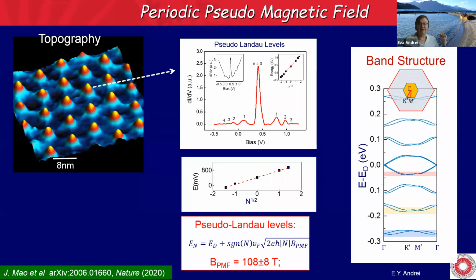Now, this is the band structure that we get. Of course, something like this will give you a flat band. This is a simulation of the band structure for this pseudomagnetic field, and you get a sequence of flat bands. In principle, if you can bring the Fermi energy into these flat bands, you should be able to open a pseudo gap here. In this particular sample, we were not able to do it because the substrate was niobium diselenide. It was a conductor, and you can imagine that we were not. The reason for doing this experiment was not to look at the buckling transition. However, we got a lucky break here. Now we have a new experiment where we put the graphene on boron nitride, and we saw indeed the pseudomagnetic fields. We were able to bring the Fermi energy within the peak here and see a pseudo gap open.